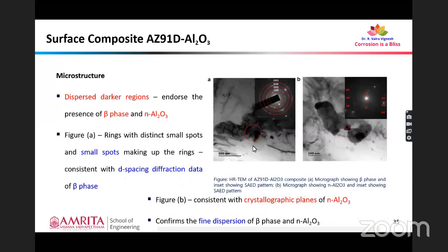Similarly, we have done analysis over the nanophase particles too, and we have confirmed the fine dispersion of nanophase alumina and beta phase inside the surface composite. In figure A, we can see the rings with distinct small spots making up the rings. This is consistent with the d-spacing diffraction data of beta phase, and added to that, the inset in figure B shows the SAED pattern of that particle. When we indexed that particle's SAED pattern, it was found to be nanophase alumina. From this we can confirm that there is fine dispersion of beta phase and nanophase alumina inside the matrix, and there is formation of dislocation tangles and subgrains within the microstructure of the material. So we have a refined microstructure and confirm the presence of beta phase particles in the surface composites too.